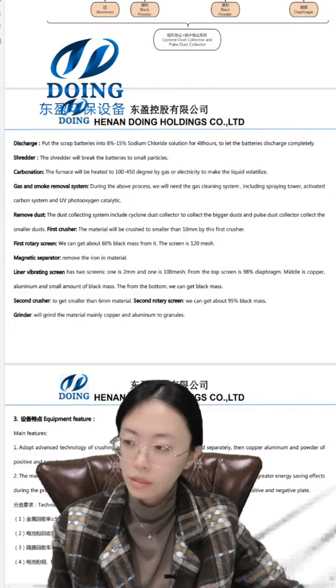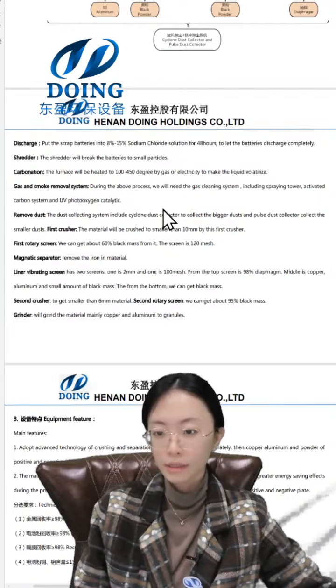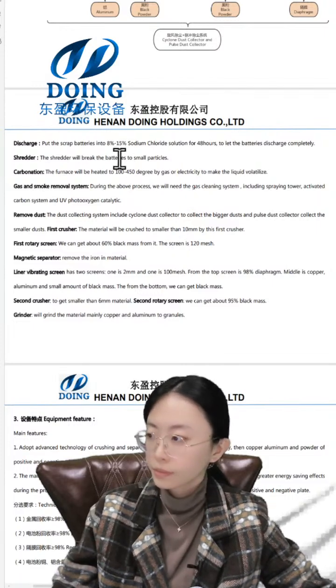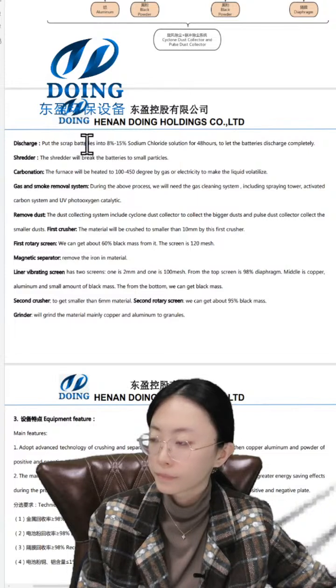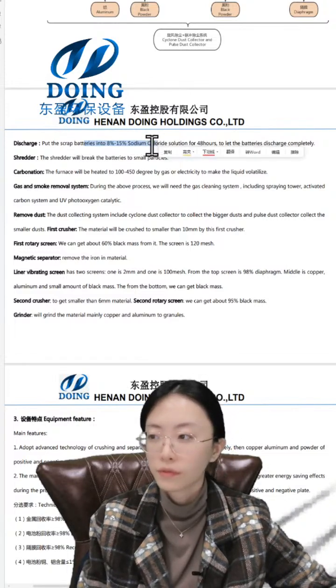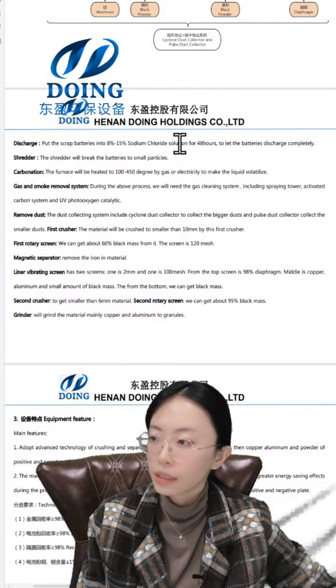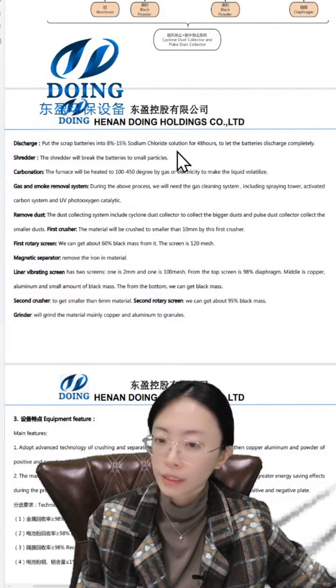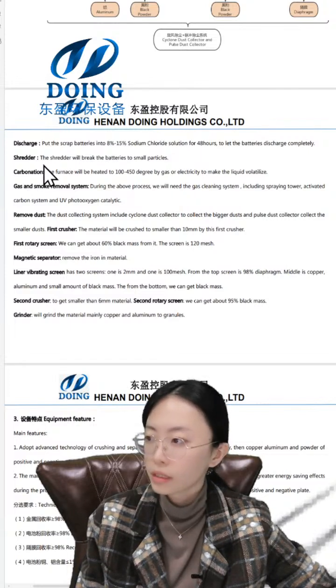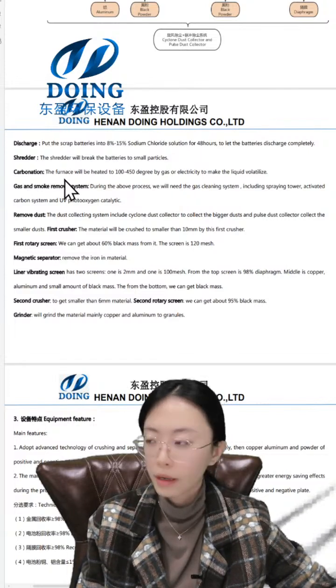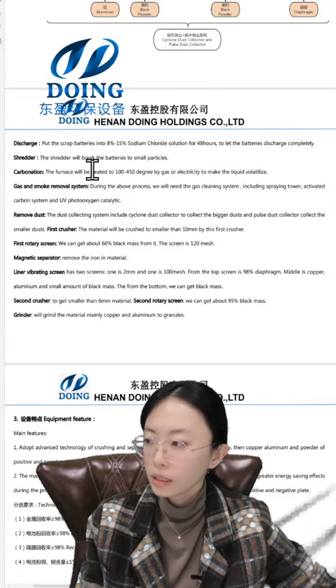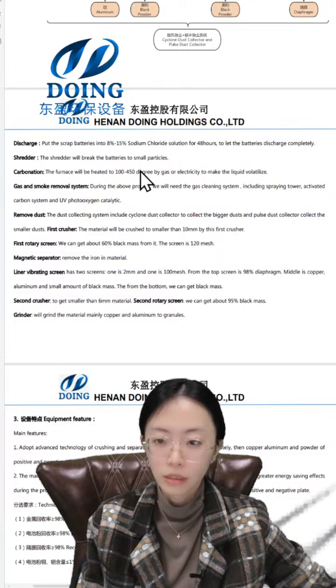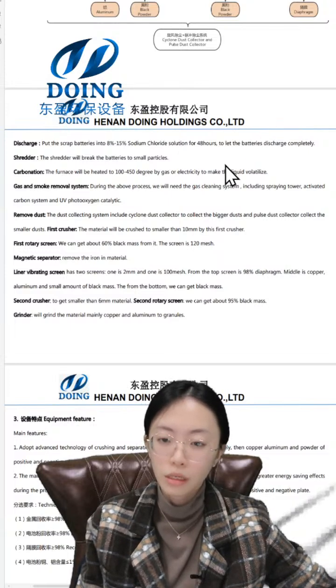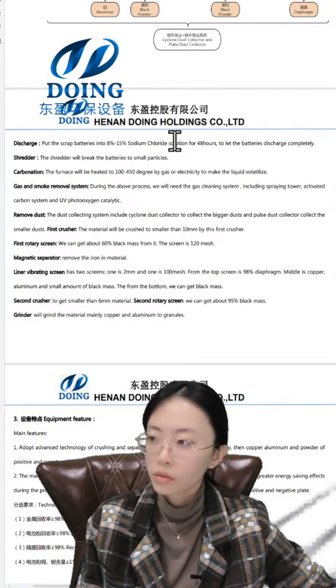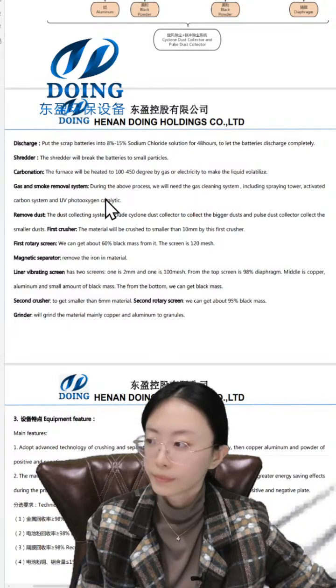Here is a brief introduction of our lithium battery device. And the first is discharge. You put it into a 6 to 15% sodium chloride solution for the safety process. And then the shredder breaks the battery into small particles. The carbonation furnace heats to 100 to 450 degrees to evaporate the electrolyte and also the chloride solution.